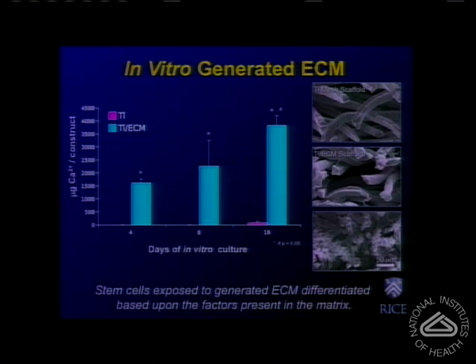So when we culture fresh mesenchymal stem cells on these constructs under flow perfusion conditions, we experience production of enormous amounts of extracellular matrix as the result of the signaling that was provided by the extracellular matrix that was deposited on the surface of the titanium. So this is essentially a paradigm shift in the biomaterials field that relies on the use of cell culture and bioreactor technologies to transform an inert biomaterial into a highly active biomaterial.